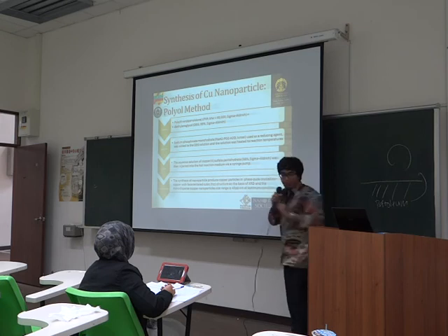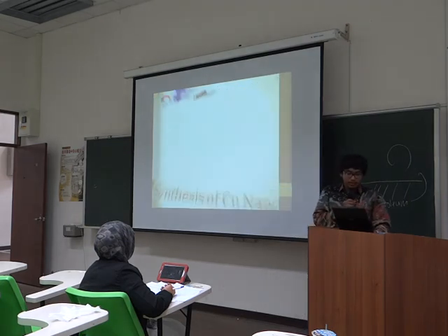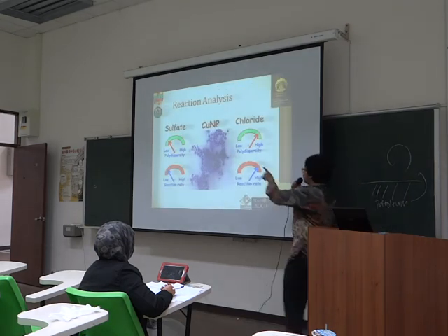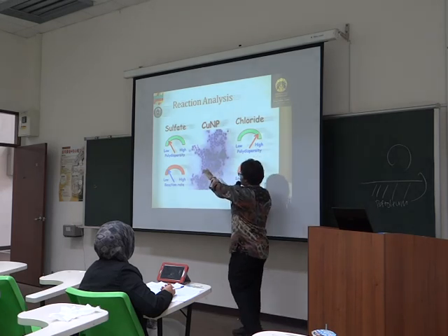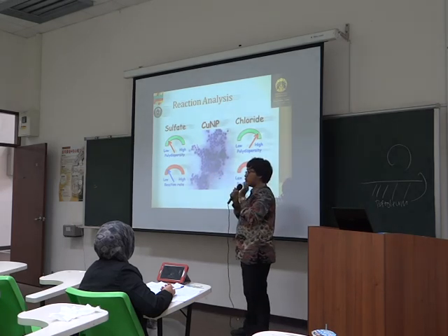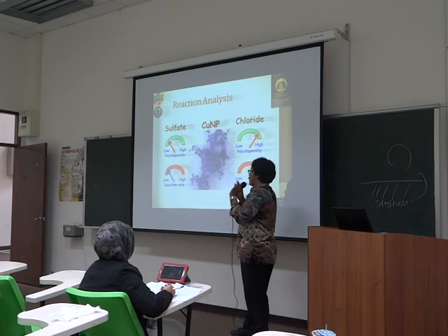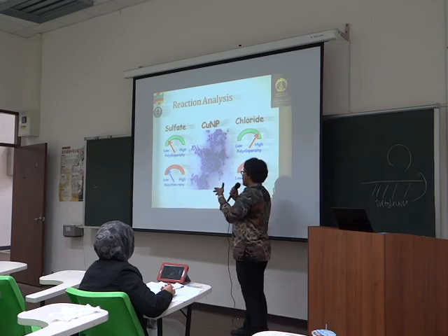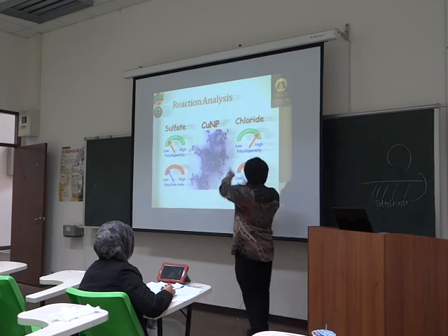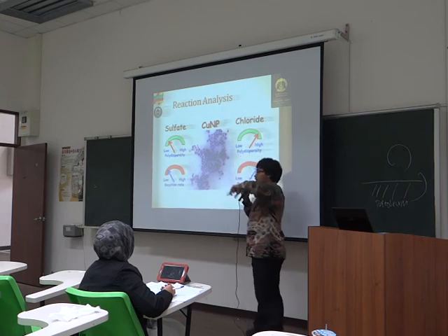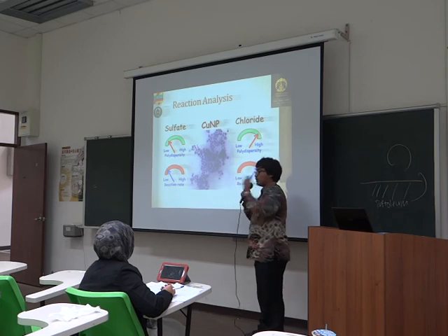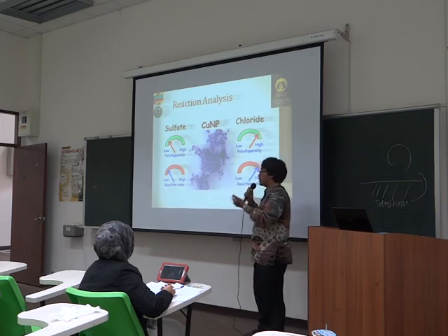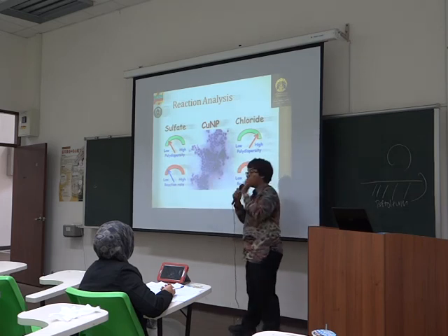It's monodispersed, because we can see here that if we use sulfate, we can have low polydispersity, which means monodispersed. The size is about 100 nanometers, and the range is 100 to 150, so the range is not so far. But if you use chloride, the result will be 100 to 200, so it's far. We want to use 100, so we use this to have monodispersed 100 nanometers.